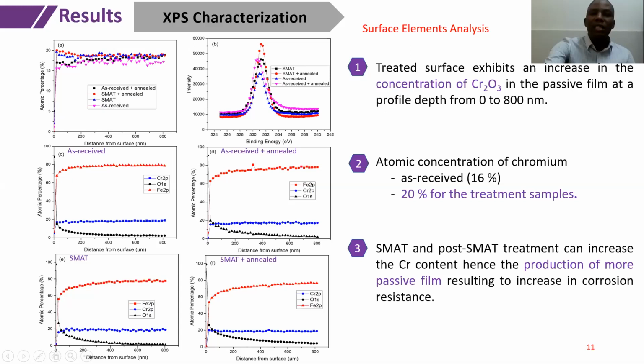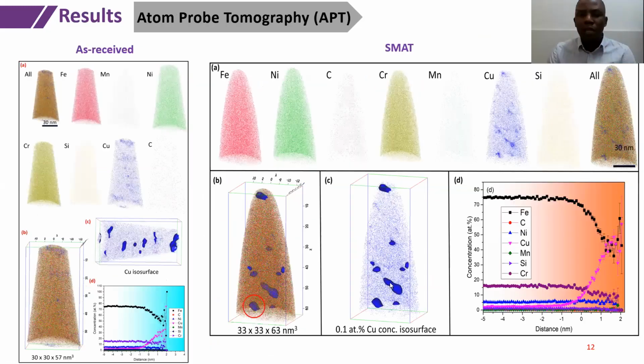And also the APT study shows that we have so many elements in the sample, which leads to uneven distribution of elements. But in particular, we have one element, which is a very high density copper-rich precipitate, and this precipitate contributes to the improved properties of the sample in terms of corrosion properties.